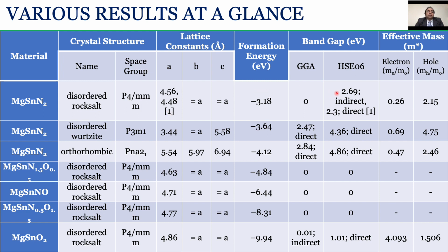Similarly, its band gap has also been calculated to be 2.69 electron volt, which closely matches the experimental result of 2.3 electron volt. We have also done formation energy analysis, where we found that the orthorhombic crystal structure has the lowest formation energy, which makes the other two crystal structures energetically metastable.